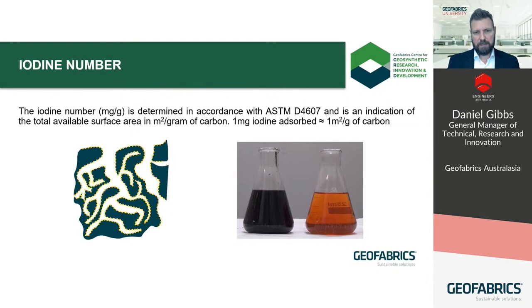So for every milligram of adsorbed iodine in the test, this roughly translates to 1 square meter for every gram of carbon. So the minimum iodine number for the activated carbon used in Saltseal is set at greater than 1,000 milligrams per gram, which translates to around 1,000 square meters per gram.